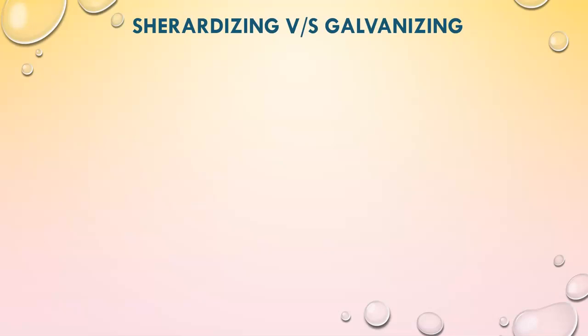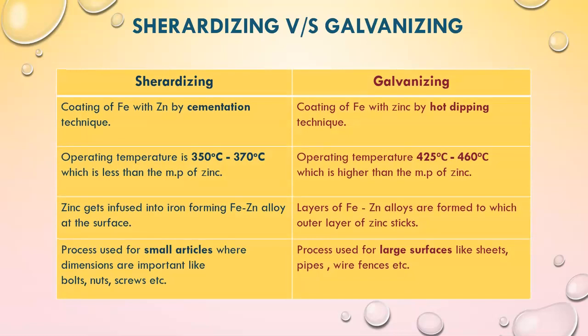Now let us compare the process of sherardizing with galvanizing. Sherardizing is coating of iron with zinc by cementation technique, while galvanizing is coating of iron with zinc by hot dipping technique. The operating temperature for sherardizing is 350 degrees Celsius to 370 degrees Celsius, which is less than the melting point of zinc, while the operating temperature in case of galvanizing is 425 degrees Celsius to 460 degrees Celsius, which is higher than the melting point of zinc, that is 419 degrees Celsius.